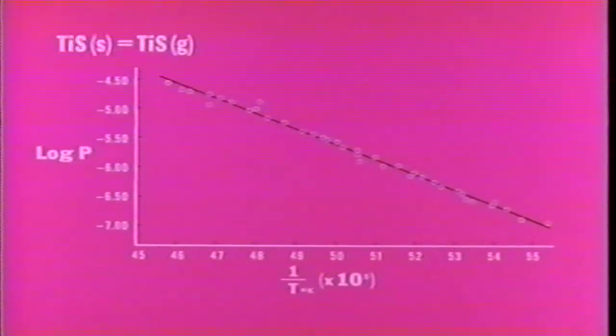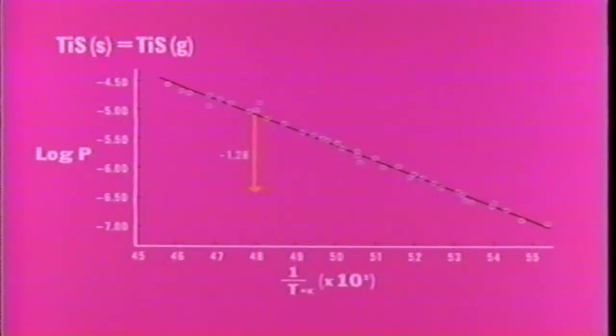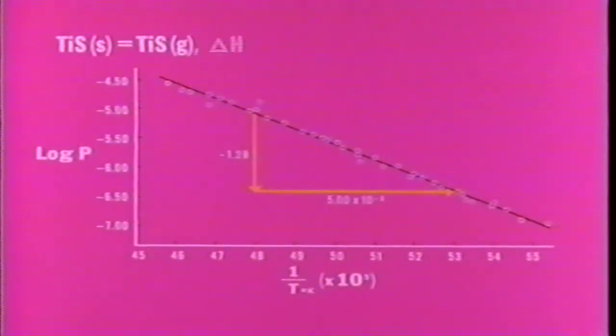This plot for solid TiS forming gaseous TiS indicates high pressure at high temperature, falling off rapidly as the temperature falls. The logarithm of the pressure decreases by 1.28, while the reciprocal temperature is increasing by 5 times 10 to the minus fifth. The change of pressure with temperature is related to the heat of reaction. In fact, the heat of reaction, delta H, is equal to a constant K times the slope S of the experimental curve. The constant is equal to minus 4.58 times 10 to the minus 3, which has been determined from other work.